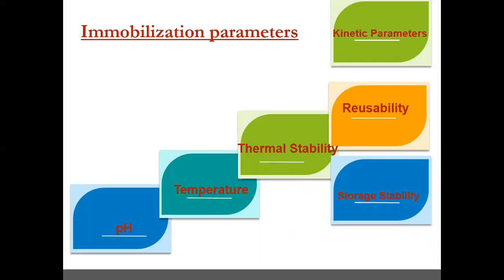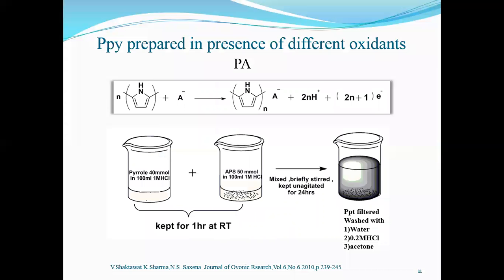Due to the endless combinations possible, outcomes reported with these factors vary widely in the literature. The main attraction of polypyrrole in the role of biomaterial stems from its electrochemical properties. Polypyrroles are initially insulators, that is, in the neutral form. It is only through oxidation, and sometimes via reduction, by chemical or electrochemical pathway that mobile charge carriers are introduced to the polymer system so as to induce conductivity. The polypyrrole backbone is neutral in the reduced state and positively charged in the oxidized state. Therefore, to maintain electric neutrality, some counter ions are required to diffuse into the polymer substance, and over-oxidation may lead to loss of conductivity and de-doping.